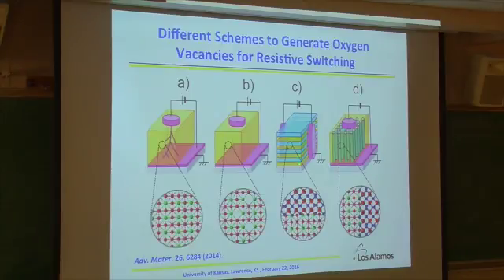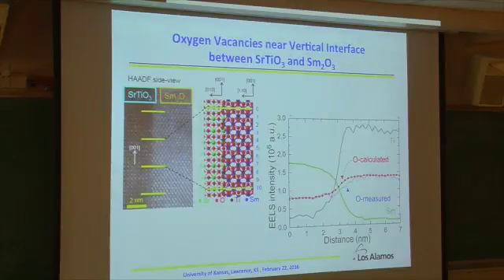Or people do superlattice, where you have to put a contact like this, and they study the interface. But with this pillar structure, it's more accessible, I would say. So you can get some very, very interesting phenomena across the interface. Over here, I just show you how the vertical interface matches together in the TEM cross-section.